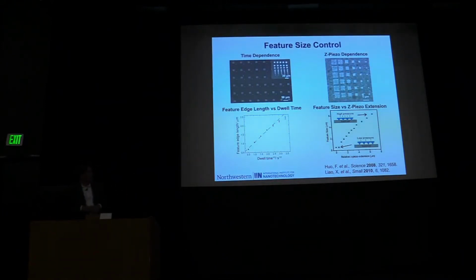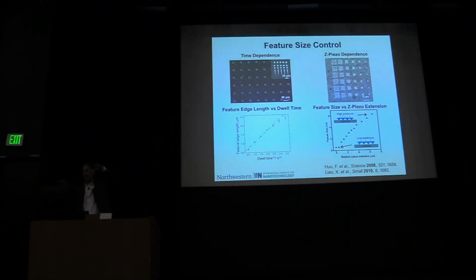Well, it turns out that it's a remarkably forgiving technique. If you think about this, leveling is critical. You have to be level, because if you're not level, you can tip the array, and these tips will hit first, and these guys won't, and then also sort of gradient in the middle. I'll come back to that concept in a second. But what we found was this architecture is really quite critical in the sense that the initial contact force is absorbed by the base of the array, kind of like a gel pad in your shoe.